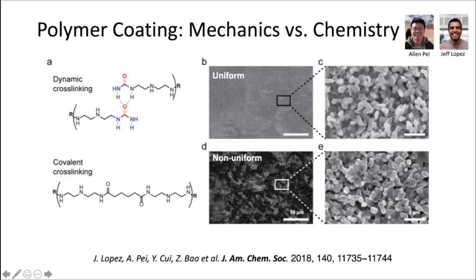So with those, we started to study what is really the role of the chemistry and also the mechanical property of these polymer coatings. And we found that one very important role of the polymer design, having the dynamic cross-linking, is that macroscopically, we can achieve a much more uniform lithium deposition without the non-uniformity that may arise if we have a rigid polymer. Even though the polymer chemistry is almost the same, the non-uniformity of the polymer and the subsequent SEI formation could lead to macroscopic regions of non-uniformity of the lithium growth, even though in the local region, we see the same chemistry give similar